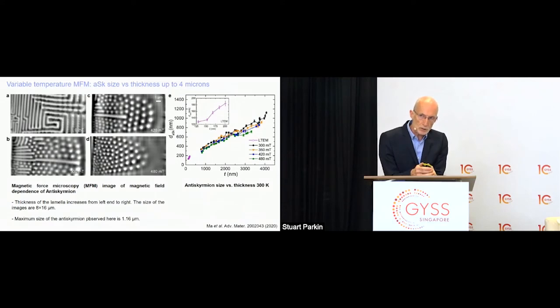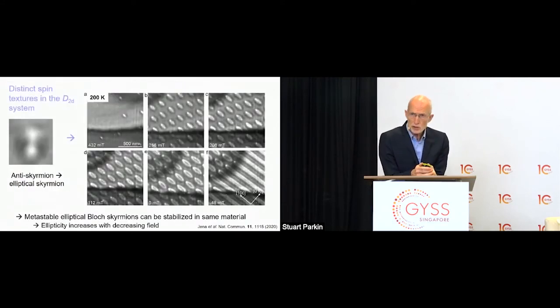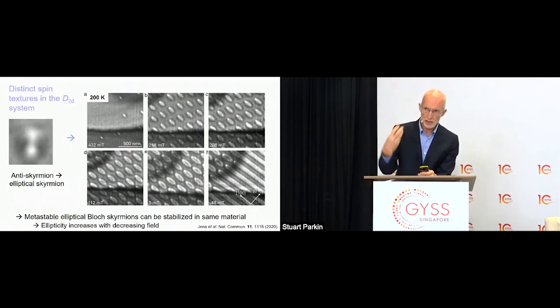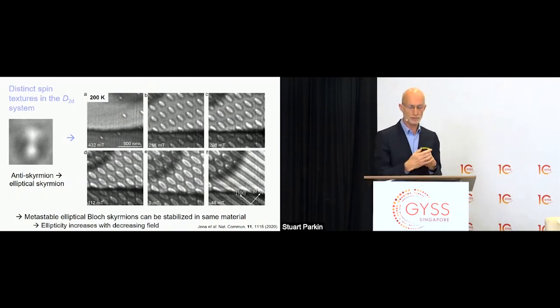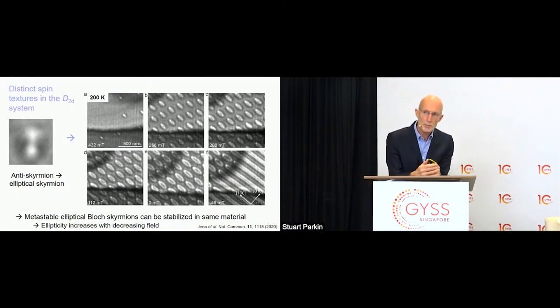This had previously not been seen. Now, it turns out these spin textures, why skyrmions and anti-skyrmions are interesting, is that the spin textures are topological. That means it's very difficult to distort them into any other structure. But we found in this system a new type of topological spin texture, these elliptical Bloch skyrmions, which are oriented along two distinct crystal directions.